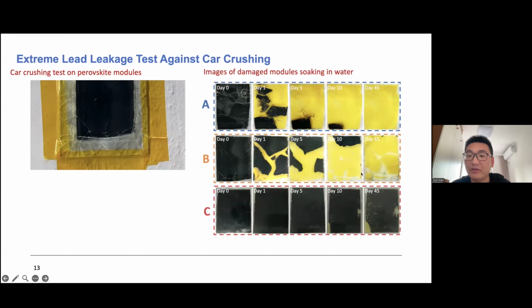the time to 45 days, and we could see the change of the color. Actually, the change of color means how much perovskite has been dissolved or damaged by water. And this time we could see this yellow color change for our aerogel-based encapsulant.